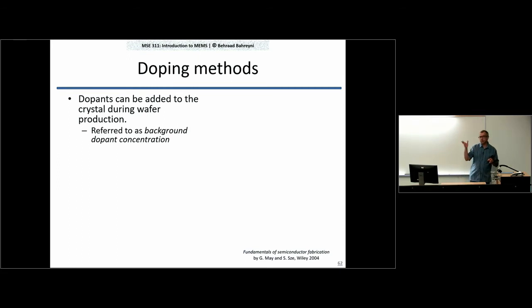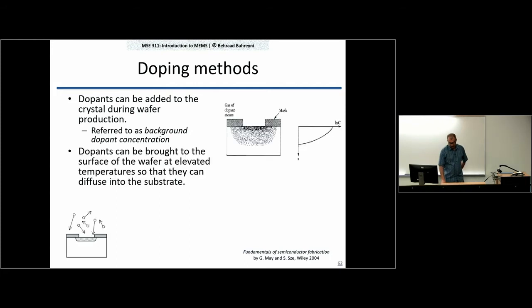But you don't have that much control over there, because we saw that the dopants tend to stay in the melt, so you get non-uniform doping across the ingot as you produce it. And also the issue is that, okay, so you have such and such doping on your wafer. Now what? You want to modify that doping. You don't want to just have a constant level of doping across the wafer. So this we do, and we call it background doping, but what is more useful to us is selective doping, that we change the doping at certain locations on the wafer as we need.